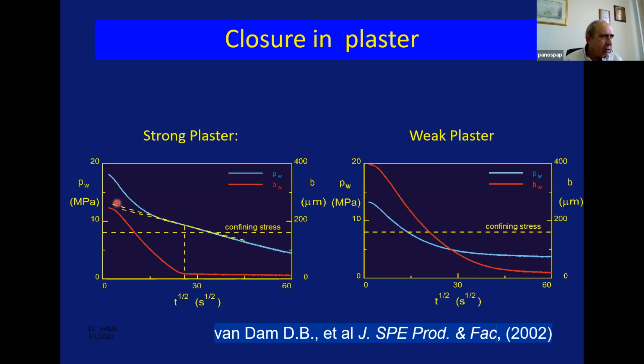In the case of the strong rock, you will see that when the pressure in the fracture drops near the confining stress on the block, the fracture had closed. You can see here in the red line that the fracture had closed. We are quite close.